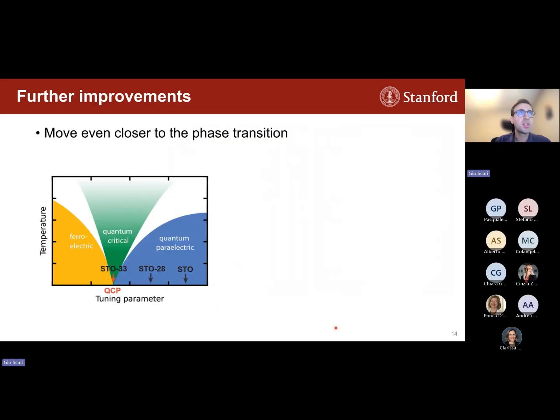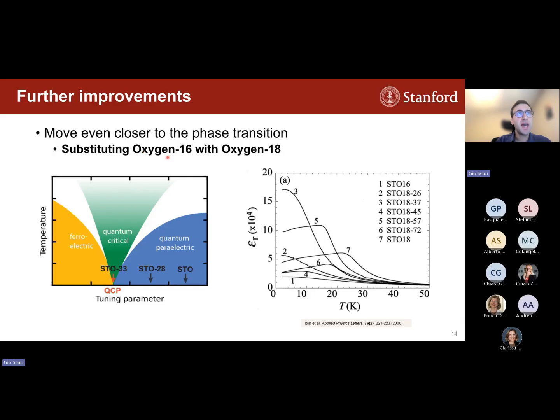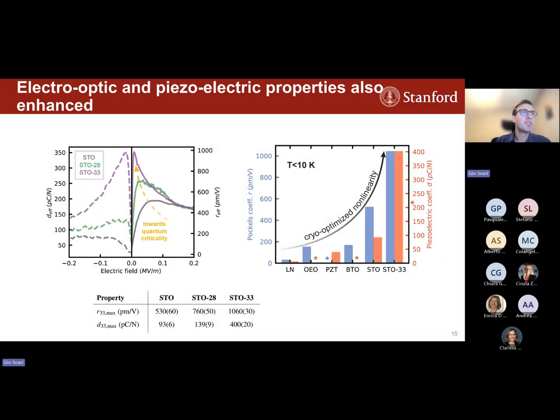And it turns out that you can use this intuition that you want to be close to phase transitions to even further improve these optical nonlinearities in the system by moving even closer to a quantum critical point or this phase transition point. One of the ways to do this is actually to substitute the naturally occurring oxygen-16 isotopes with oxygen-18. Again, there's been some research in the context of dielectric constant and other physical properties that has shown indeed this enhancement as you approach around 37% oxygen-18 ratio in the system. And together with our collaborators, this is exactly what we did. We tuned the oxygen-18 ratio in the system to around 33% and saw a drastic enhancement in both the Pockels coefficient and the piezoelectric coefficient to over 1,000 and around 400 actually at some temperatures for our system.